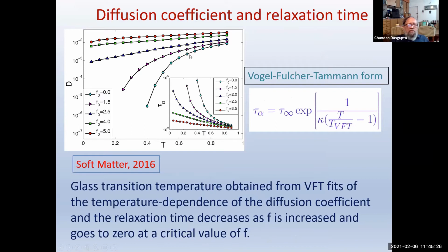As you can see, the diffusion constant is dropping very fast, and it will go to zero eventually as you go to lower temperatures. Or the relaxation time is increasing, and it will increase according to this. So we fit this relaxation time, for example, to this Vogel-Fulcher form, which predicts a divergence at a temperature TVFT. By fitting this form, we can get this TVFT, the ideal glass transition temperature. And you can also get this parameter kappa, called the fragility parameter. We can also do similar fits to the diffusion constant, and then you can extract similar parameters.